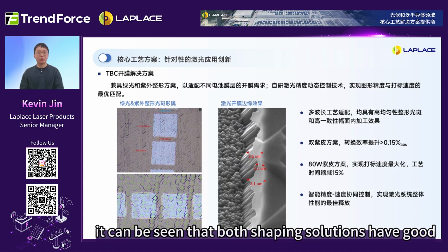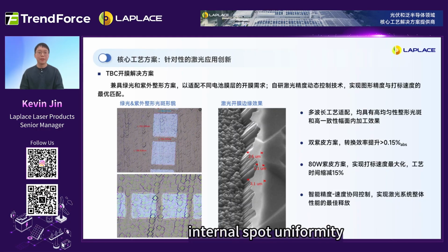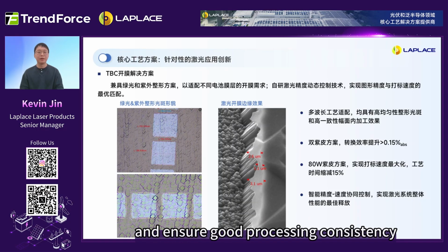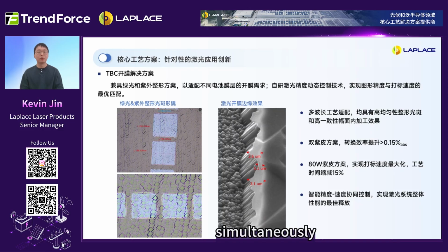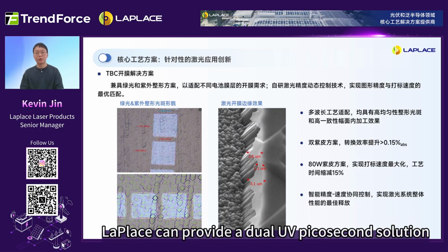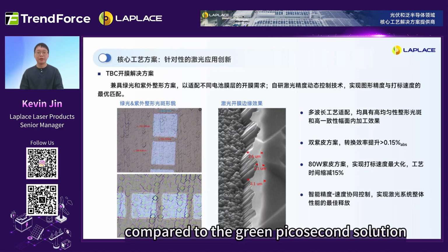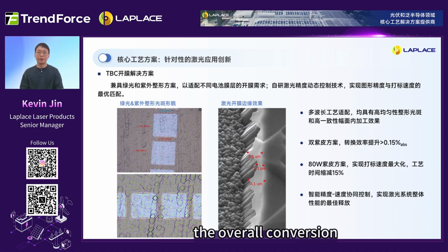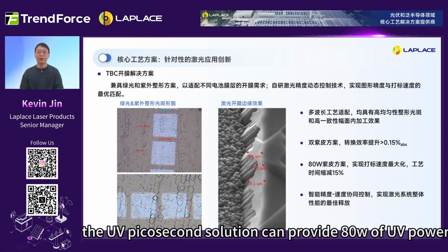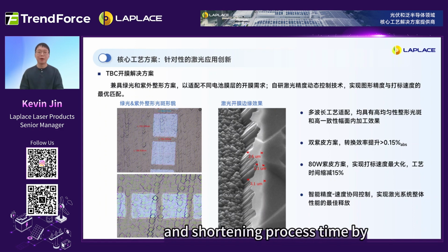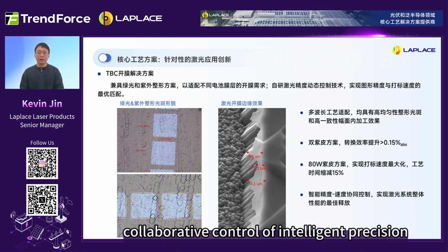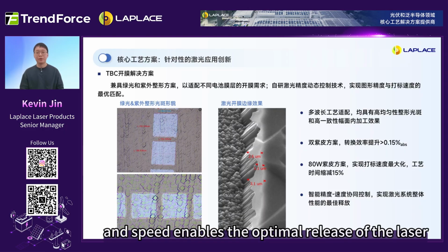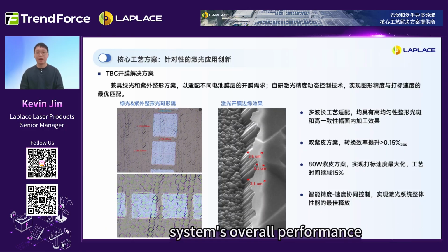It can be seen that both shaping solutions have good internal spot uniformity and ensure good processing consistency within the field of view. Simultaneously, Laplace can provide a dual UV picosecond solution. Compared to the green picosecond solution, the overall conversion efficiency improvement can reach over 0.15%. The UV picosecond solution can provide 80 W of UV power, maximizing marking speed and shortening process time by 15%. Regarding control, collaborative control of intelligent precision and speed enables the optimal release of the laser system's overall performance.